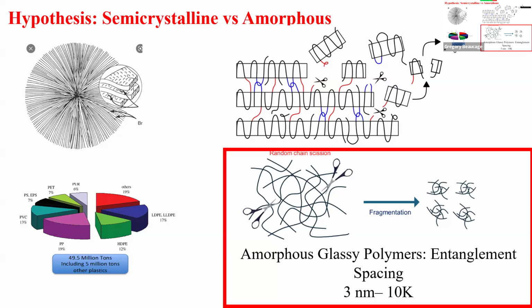Now, a key thing in the semicrystalline polymer community is I have crystals, and there are some segments that go from one crystal to the other. Those are called tie chains, right? And these tie chains are really important because without the ties, the lamellae are just kind of hanging out, doing their own thing. By tying them together, you get crystal, amorphous, crystal that are tied together, right? Hence tie chains. So imagine if I go in there and randomly start breaking bonds, I'm going to start breaking everything, including the tie chains. If I break all the tie chains between lamellae, the lamellae become totally free. They start flopping, and they're going to get released.